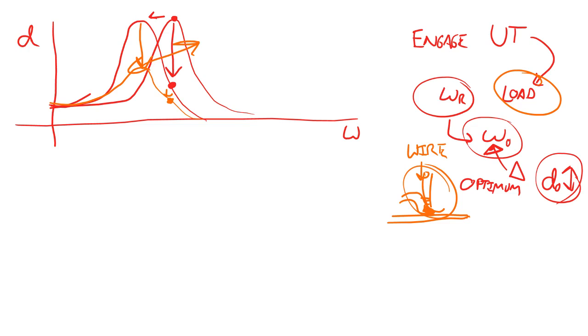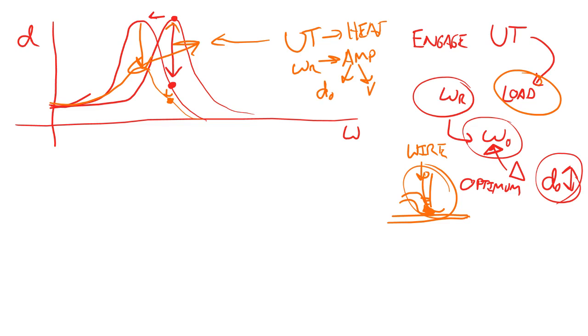You will get a very variable output if you're not driving at the proper frequency or conditions. Furthermore, as the ultrasonic transducer is driven, it heats up, and heat also shifts frequencies, causing the same effect as load. The resonance frequency also changes with drive amplitude — both how much it's displacing and how much voltage you're putting in. All of these effects create a variable response in the piezoelectric device.